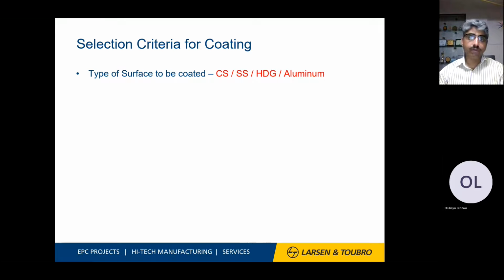The criteria for coating: first is the substrate material, or you can say the base metal. Whether it is carbon steel, stainless steel, hot dip galvanized steel, or non-ferrous aluminum surfaces. So any surface you can coat. For example, aircraft is made of aluminum, lithium, copper alloy, so you find good coatings over the aircraft. That is nothing but a coating on aluminum. Hot dip galvanized pipelines, for fire safety lines, are painted.